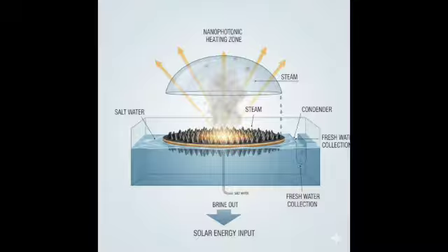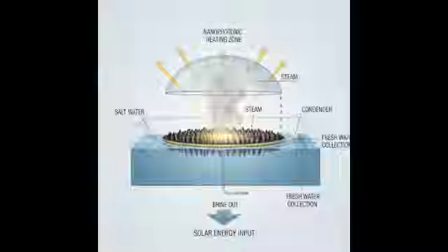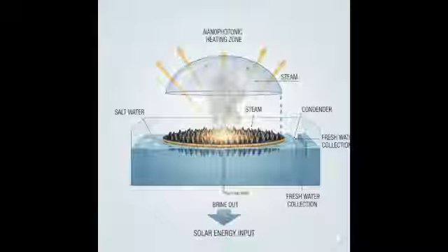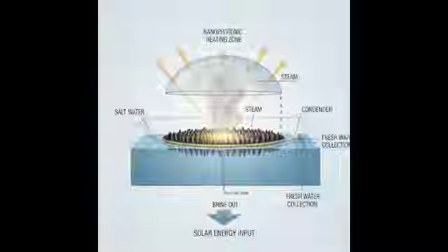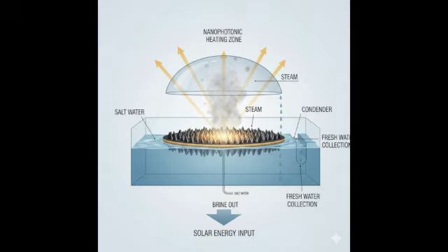PMD uses these photothermal materials, nanoparticles, special coatings, integrated directly onto or into the membrane. Think of them as tiny, nanoscale heaters embedded right where you need them. And they're powered by sunlight. Correct. They absorb incoming solar radiation very efficiently and convert that light energy directly into heat. Critically, this heating happens at the membrane surface. So instead of heating the bulk fluid far away, you generate heat at the interface. Precisely. And this completely flips the script on temperature polarization.